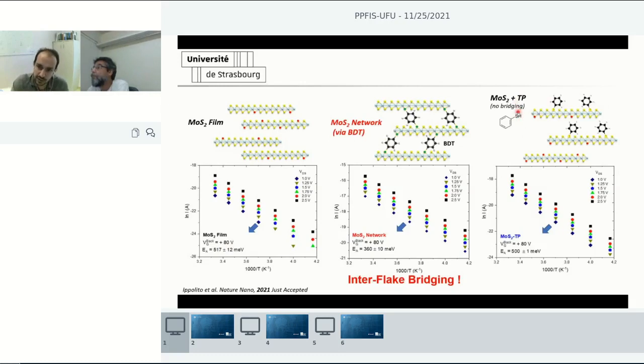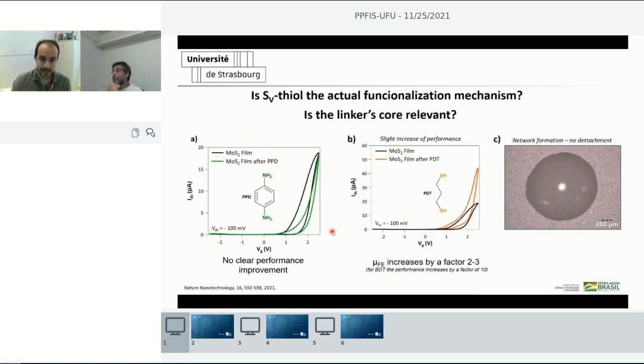If we use molecules that have only one thiol and a delocalized core, so they are able to heal the vacancies but not to bridge the flakes, what we observe is that the activation energy is quite similar to the situation where we do not have molecules. This slight decrease is because we are healing defects that are scattering centers of carriers, but we do not bridge in this case using this molecule. So there is no significant decrease of activation energy and facilitation of transport.